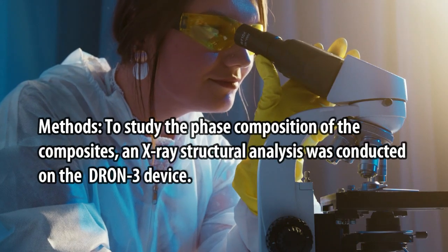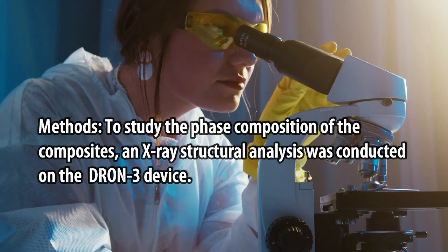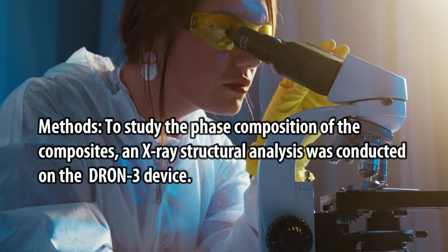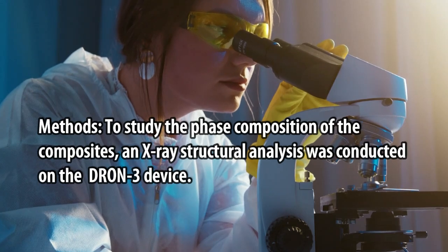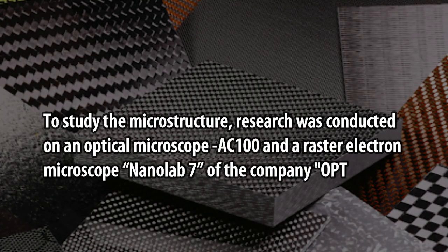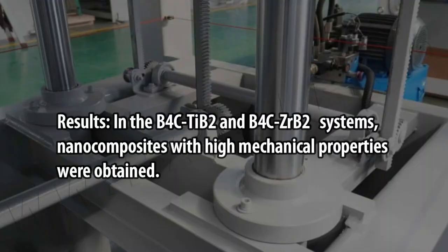Methods. To study the phase composition of the composites, an X-ray structural analysis was conducted on the Dron 3 device. To study the microstructure, research was conducted on an optical microscope AC100 and a raster electron microscope, Nanolab 7, of the company Opton. Results. In the boron carbide titanium diboride and boron carbide zirconium diboride systems, nanocomposites with high mechanical